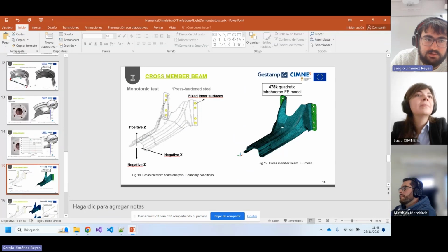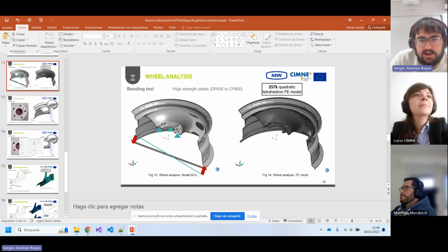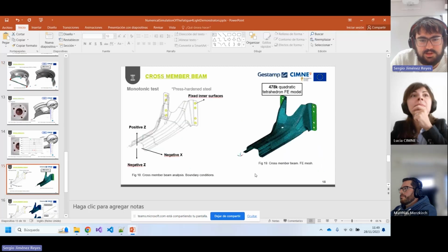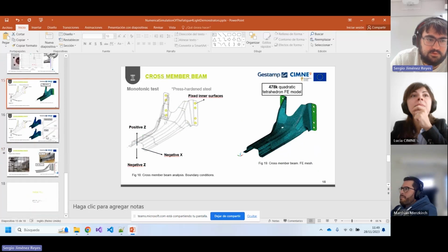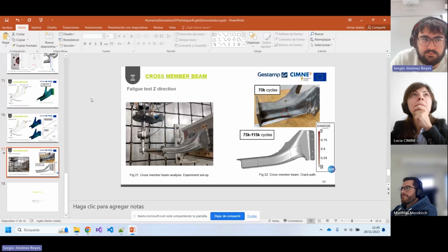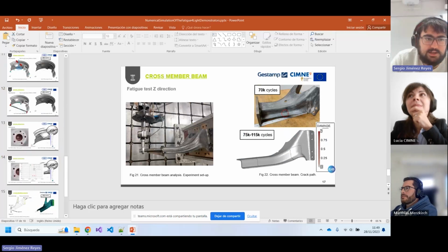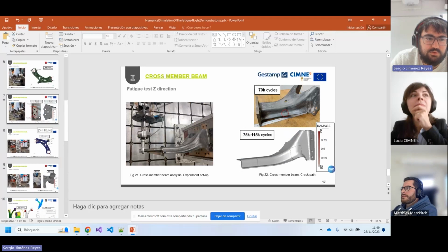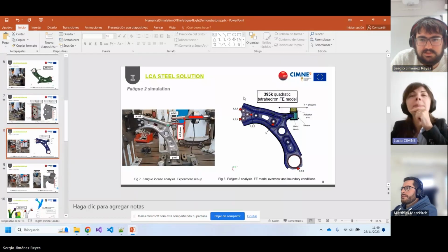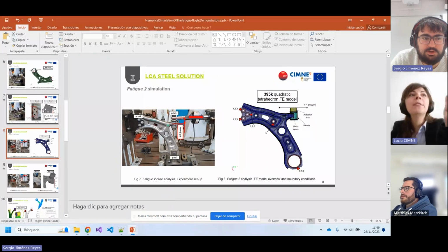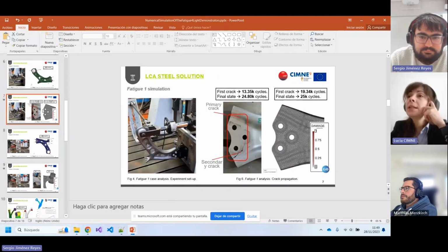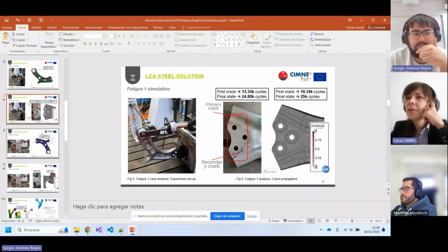But for example, in the wheel case, it takes hours to run. I spoke yesterday with Alejandro, and I think he told me that the last simulation he ran took like 5 hours, if I'm not wrong. In this case, it also took hours, not the monotonic one, but the fatigue one, which is the one that you were asking for. And the case of the lower control arm, it took 2 days, right, Lucia? Yes. In the weld, if I'm not wrong. For the weld, it took 1 day and 1 hour, I think. Okay, so it's like 25 hours.